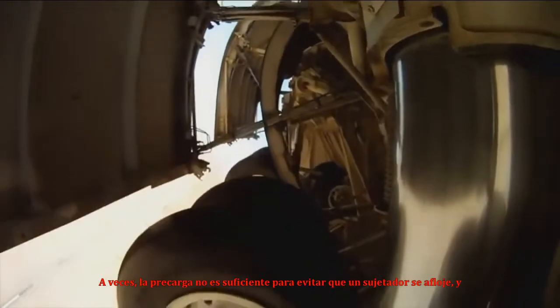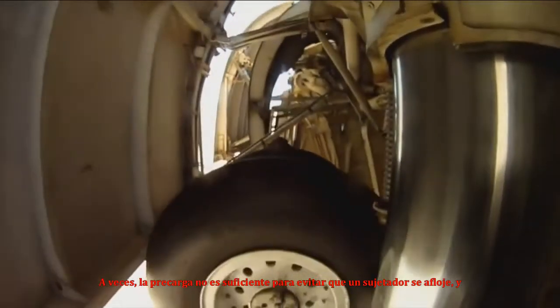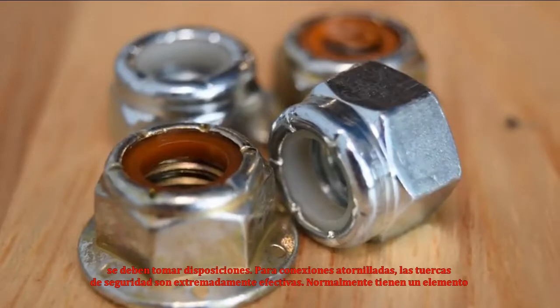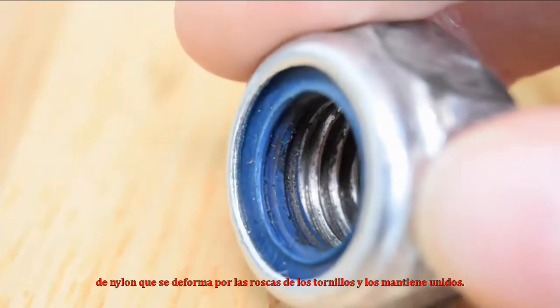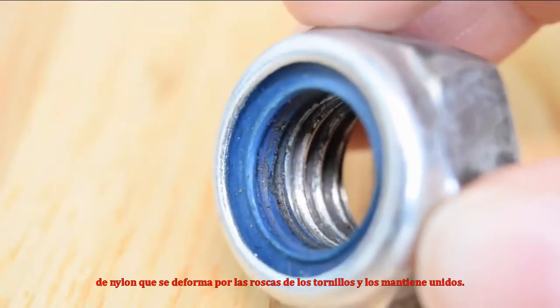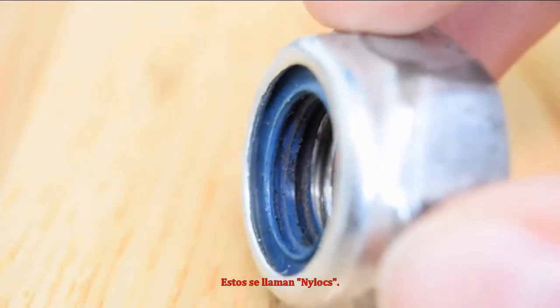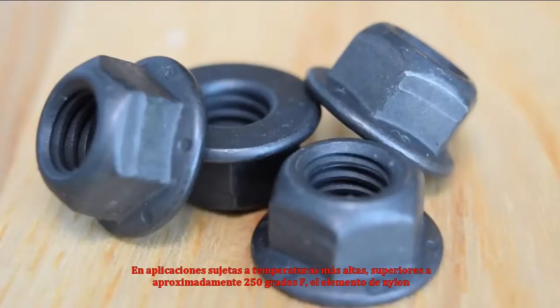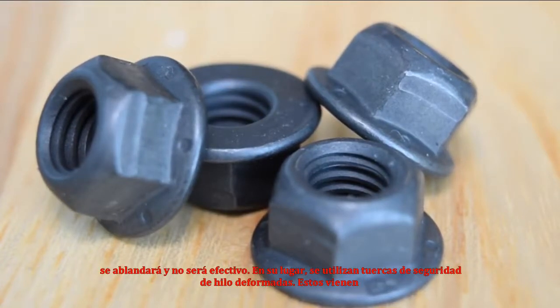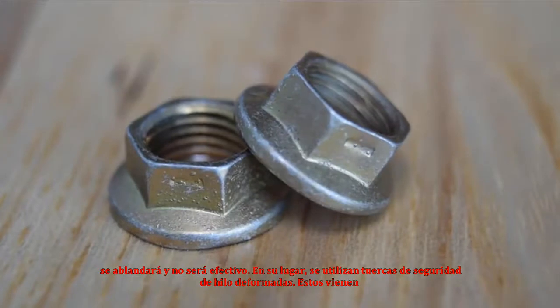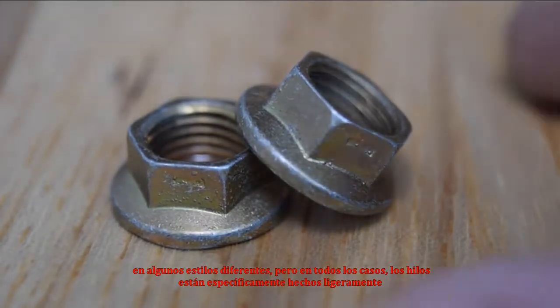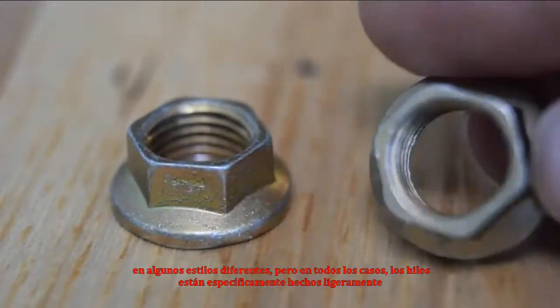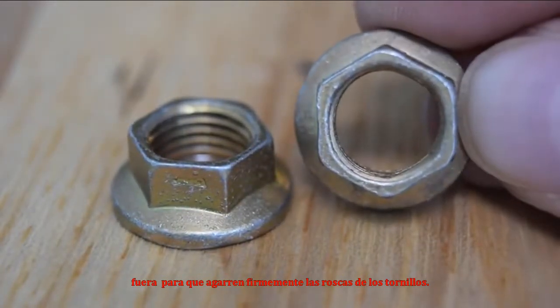Sometimes preload is not enough to prevent a fastener from loosening, and additional provisions must be made. For bolted connections, lock nuts are extremely effective. The most basic style has a nylon element that is deformed by the screw threads and holds the two together. These are called nylocks. In applications subject to higher temperatures above about 250 degrees F, the nylon element will soften and not be effective. Instead, deformed thread lock nuts are used. These come in a few different styles, but in all cases, the threads are specifically made slightly out of round so that they tightly grip the screw threads.